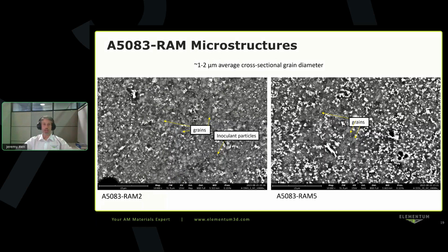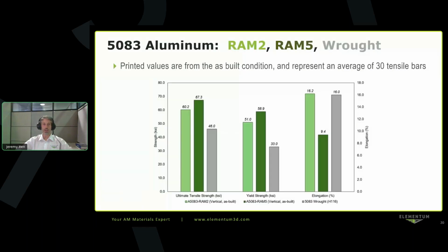So what do the properties look like for these alloys, and how do they compare to the wrought traditionally produced materials? So these are printed values from the as-built condition. In this case, 5083 is known as the highest strength commonly used aluminum alloy that does not require heat treatment to achieve the strengths. And so these green bars are our RAM 2 and RAM 5 printed materials, and they're compared in this case against the legacy wrought produced 5083 alloy in a work hardened and slightly stress relieved condition, but primarily benefiting from work hardening. And so in the printed materials, you can see even without the true work hardening, there's some internal stress from the print process, but you can see the strengths are much higher.